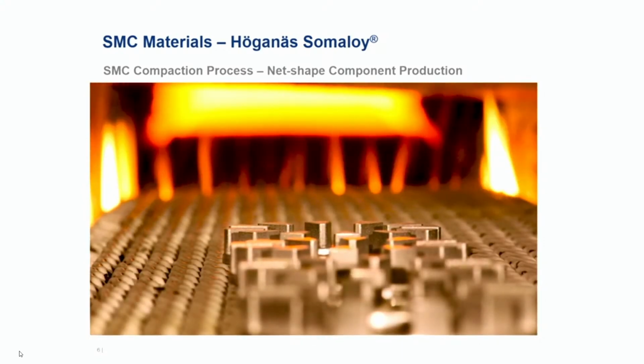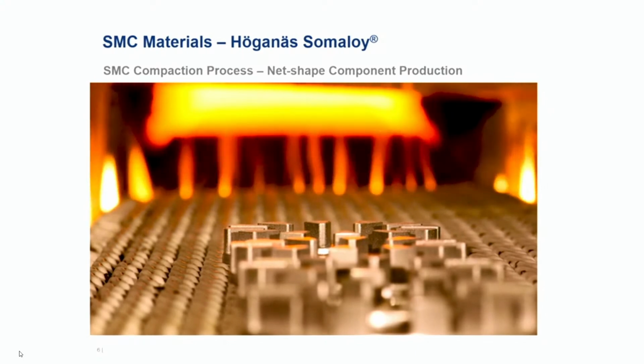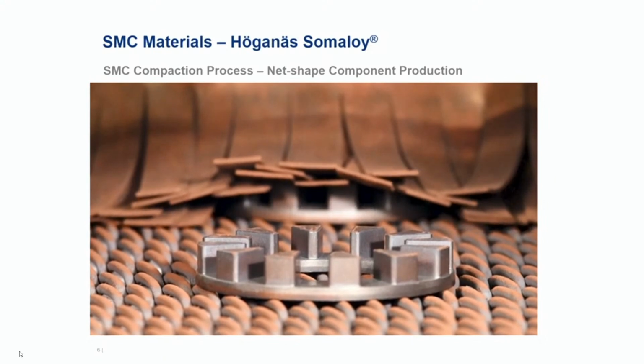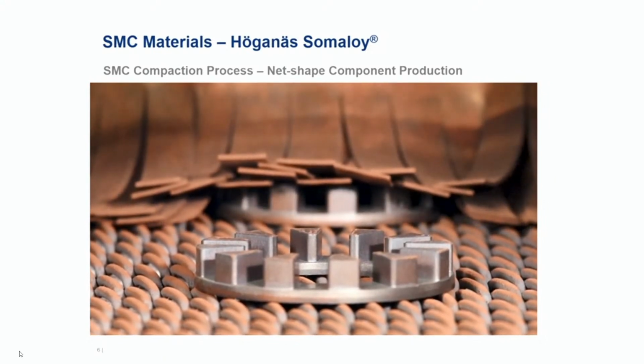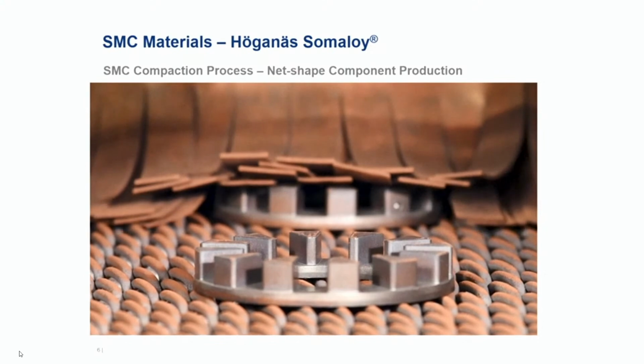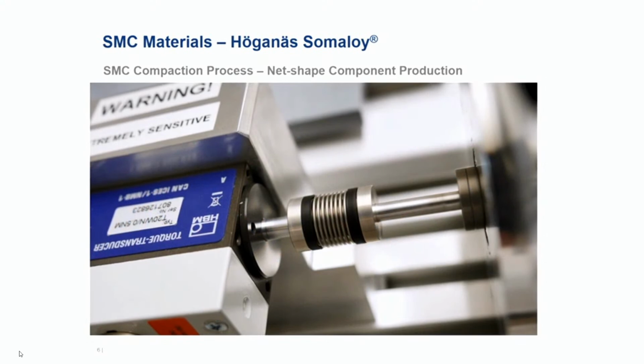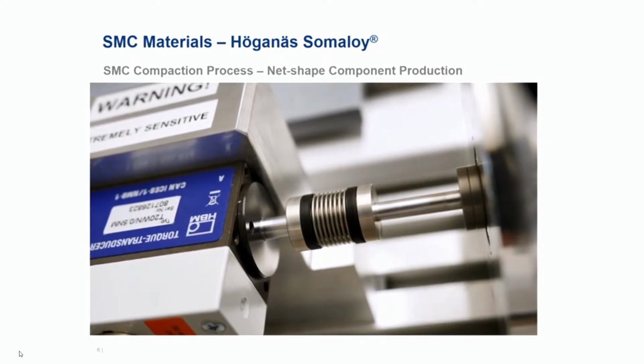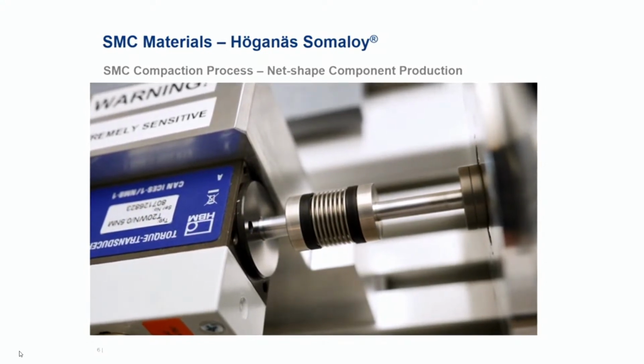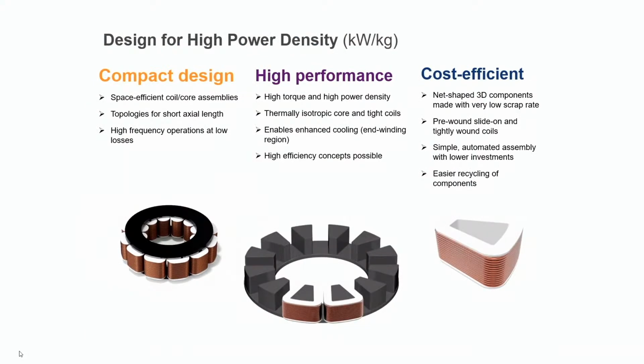For a large motor, you probably will have a higher yield, but for the powder case, we can use almost 100% of the powder. And then the component goes through the furnace for stress releasing, so you get a finished component. And then you can test the component directly in motor applications. And in this case, from the powder to the motor component, this could have quite many benefits.